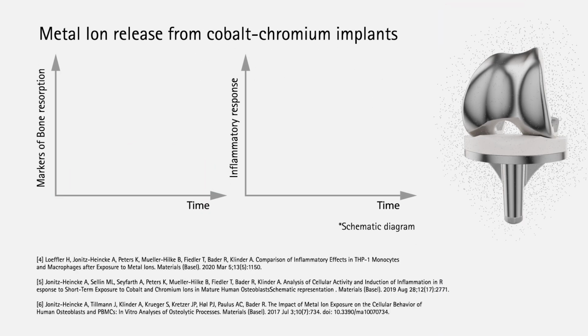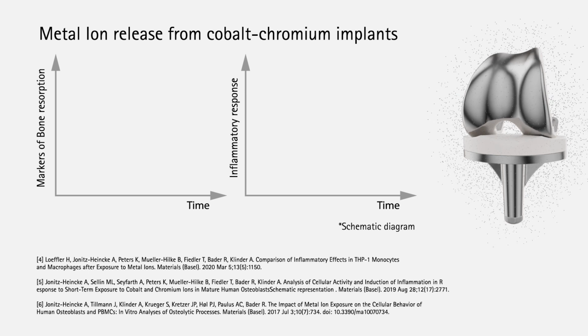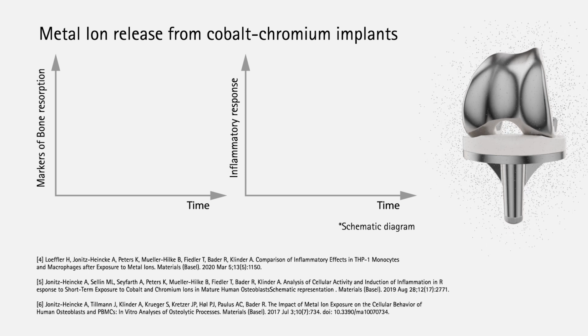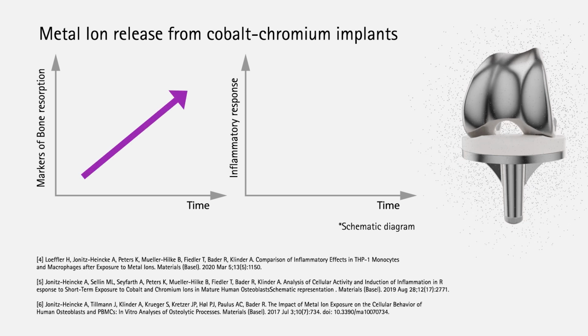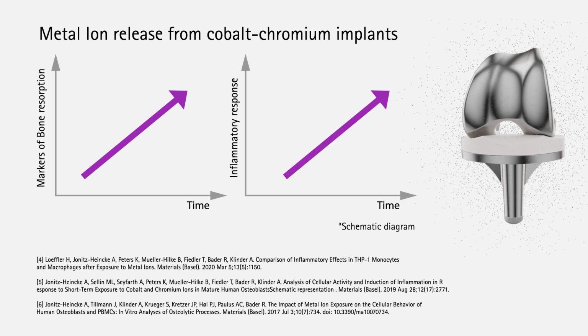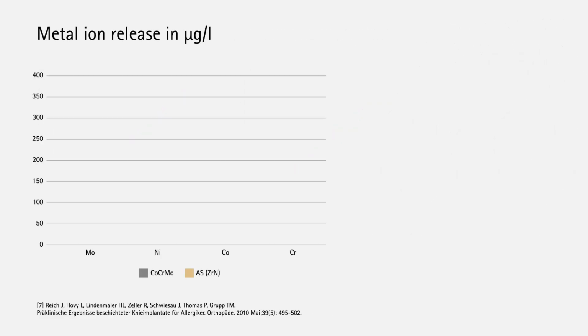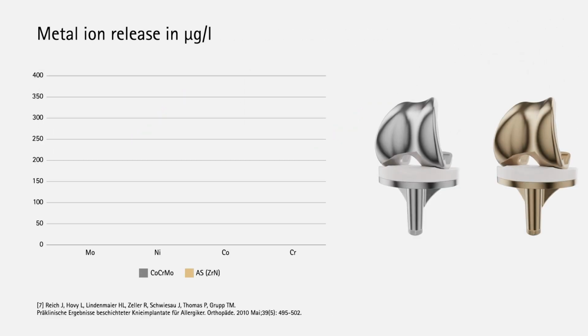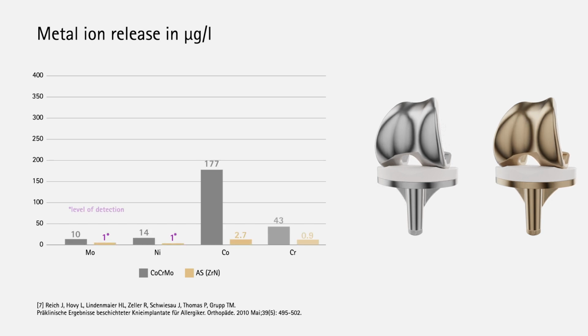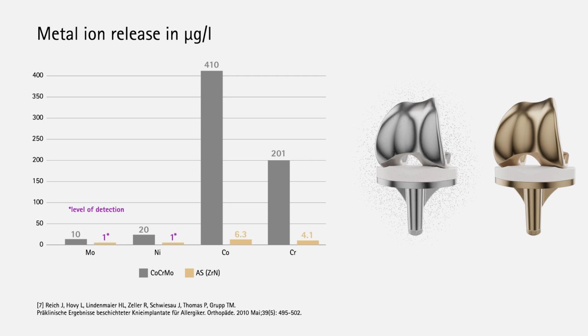In vitro studies show that corrosion products from cobalt chromium implants seem to shift the balance towards bone resorption and to aggravate the inflammatory response in bone cells. In a study of Reich et al., the ion concentration of standard cobalt chromium implants as well as AS (ZrN)-coated implants has been investigated after a knee wear simulation. The result can be seen in the graph.